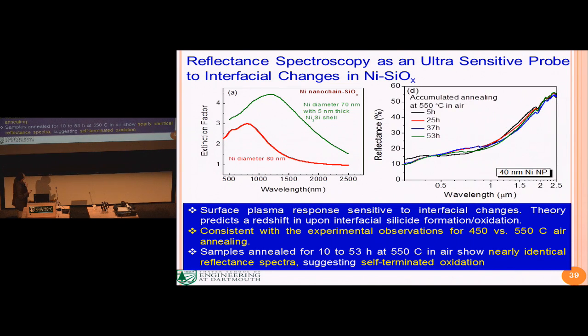We also want to verify if this is just due to kinetics, oxygen diffusion, or other mechanisms. So we make smaller particles. If it's due to kinetics, smaller particles will be easier to oxidize. However, we find the same kind of behavior. Oxidation saturates and terminates after 10 hours or so in this matrix. So that's a very interesting feature. It's telling you that you could have self-terminated oxidation in this system.